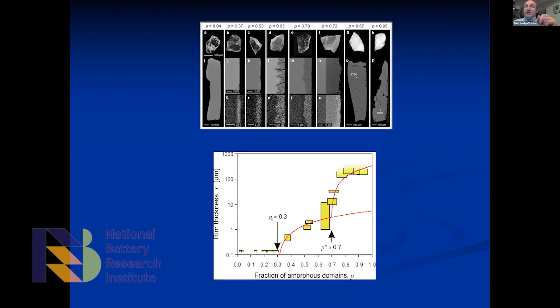The increases of diffusion are pretty dramatic, and you can see that the changes are by several orders of magnitude. That's interesting, right? Because from the point of view of encapsulating nuclear waste, we can say that here, the diffusion rates are very small. So if you put a radioactive ion in it, it will probably not diffuse too much. On the other hand, if you put it around here, the diffusion will be 100,000 times more, and it might actually then get out.